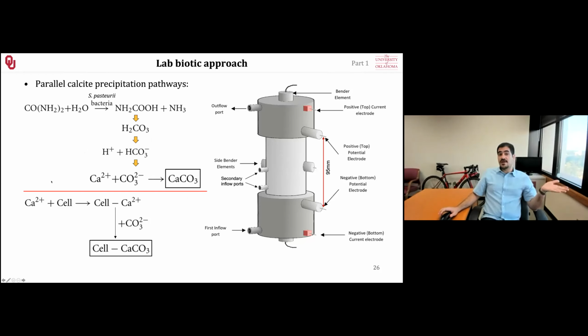So what are the right ingredients? These microbes need urea because they are capable of decomposing urea as a source of food for themselves. And when they do that, they produce carbonate. Now, if we have a rich environment that has calcium in it, it basically immediately starts precipitating calcite. So we're good here.